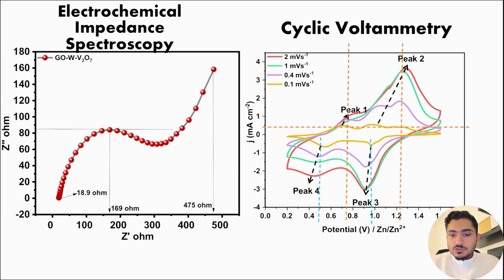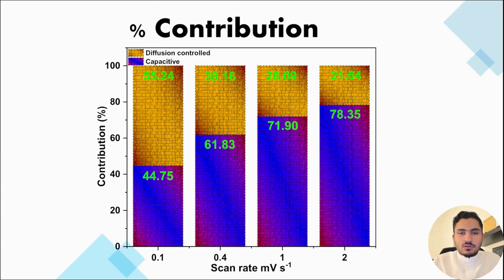The highest anodic peak shows the current of 3.5 mA, which is higher than the current of the highest cathodic peak, whereas the second anodic peak showed a current of around 1.3 mA, which is lower than the second cathodic peak. Finally, we have the percentage contribution, where the battery can either show a diffusion or a capacitive controlled behavior. At a scan rate of 0.1 mV per second, the battery showed a diffusion controlled behavior of about 55%. When we increase the scan rate to 0.4, the battery showed a capacitive behavior, and this behavior kept increasing with the increase of the scan rate.